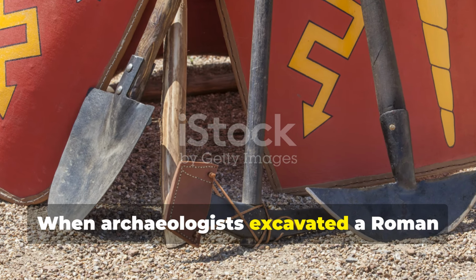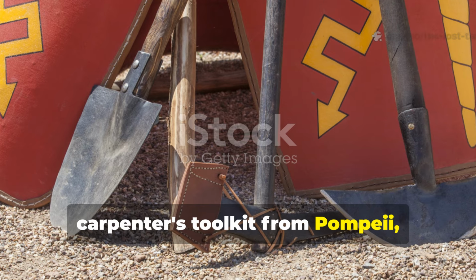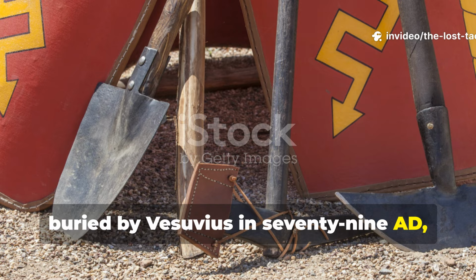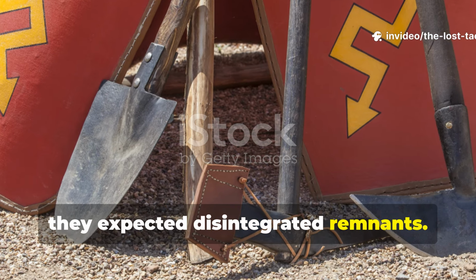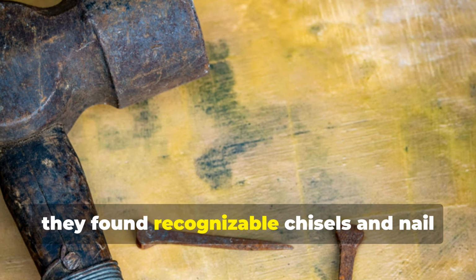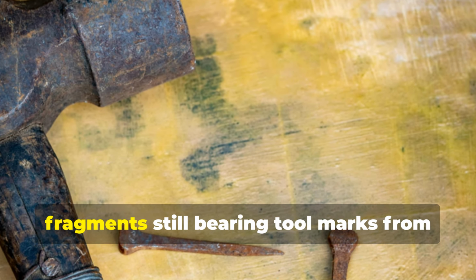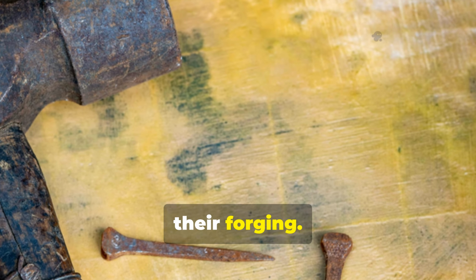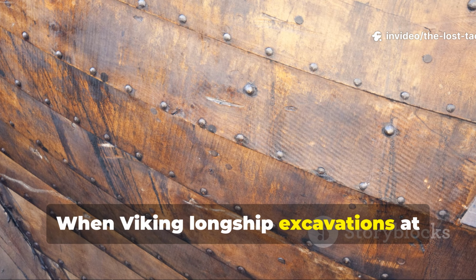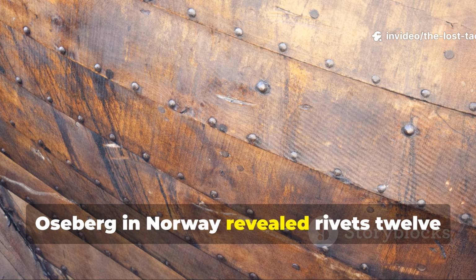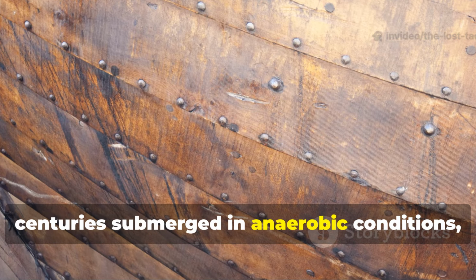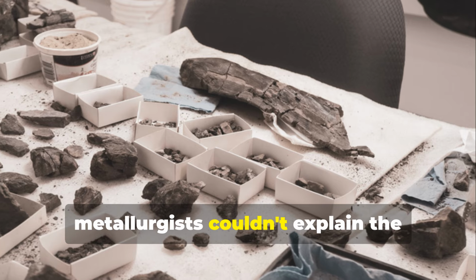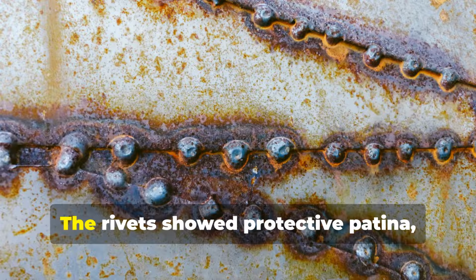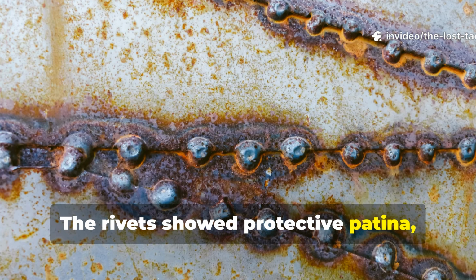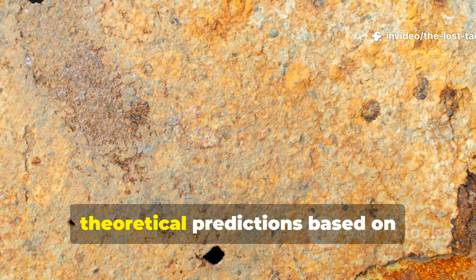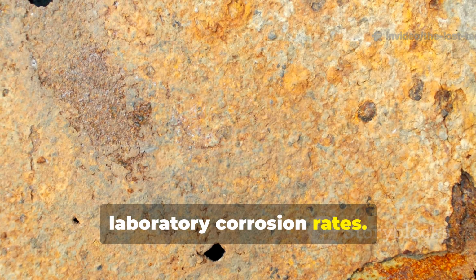When archaeologists excavated a Roman carpenter's toolkit from Pompeii, buried by Vesuvius in 79 AD, they expected disintegrated remnants. Instead, they found recognizable chisels and nail fragments still bearing tool marks from their forging. When Viking longship excavations at Oseberg in Norway revealed rivets 12 centuries submerged in anaerobic conditions, metallurgists couldn't explain the preservation with confidence. The rivets showed protective patina, but the degree of preservation exceeded theoretical predictions based on laboratory corrosion rates.